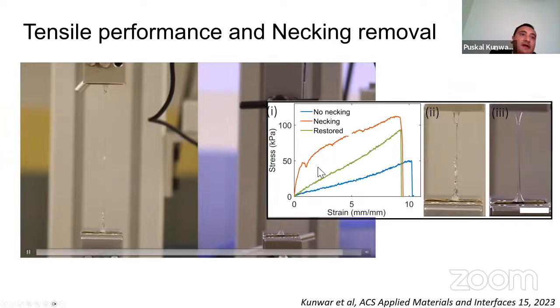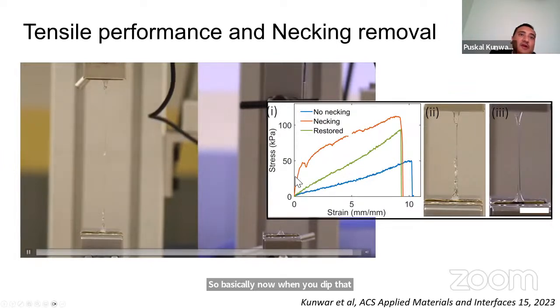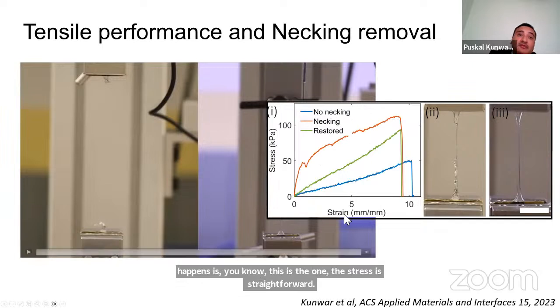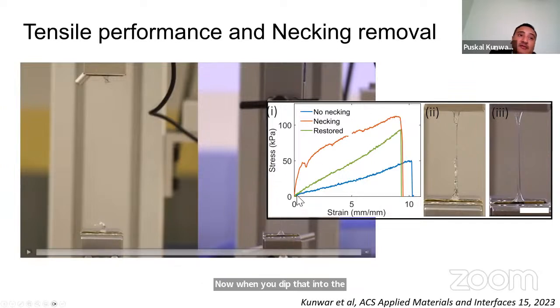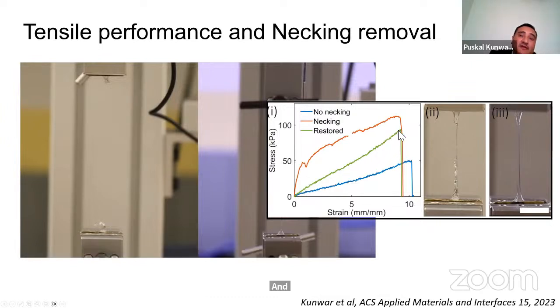So basically now when you dip that into the water, this is the stress strain curve. Now when you dip that into the water, it requires much less stress, so you lose the toughness of this structure. But what we can do is, while you prepare the sample, you can first decrease the amount of water,